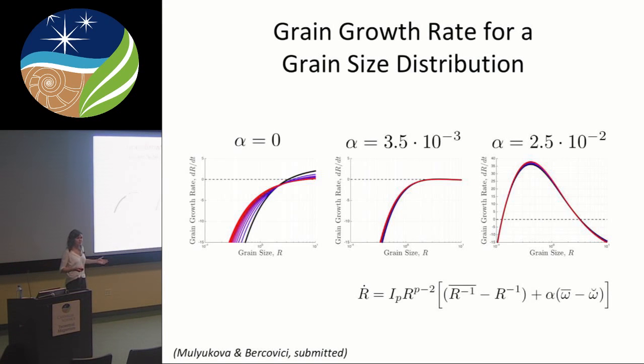We did the same experiments with the grain size distribution as we did for 2 grains. We started at alpha being 0 and increased it systematically. Here, just a simple coarsening case where small grains shrink and the large grains grow. When alpha is a bit larger, small grains can still shrink, but larger grains now don't want to grow quite as much because now they have to compete with this increase of dislocation density.